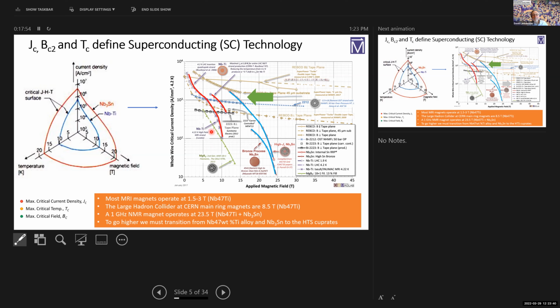Most is made of niobium titanium. It's the Large Hadron Collider at CERN. Most MRI magnets, well, essentially every MRI magnet, is made of niobium titanium. Gigahertz NMR magnets, which are a fairly large market, use niobium tin inside niobium titanium magnets. But if we want to go higher than that from a superconducting point of view, we've got to use one of these cuprate superconductors. And so you see that critical current density characteristic is much flatter and extends out to much higher fields.